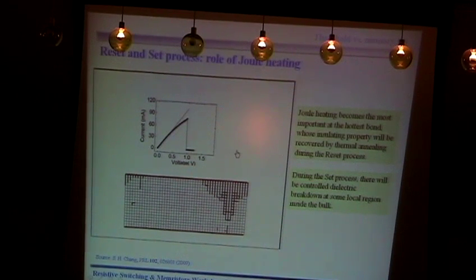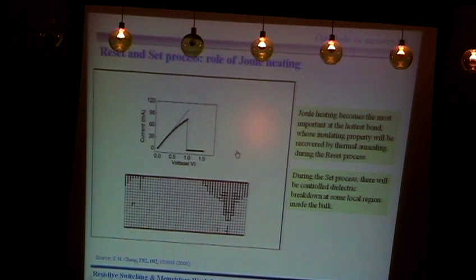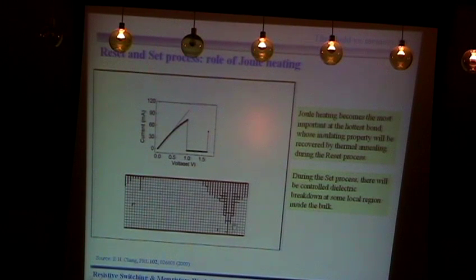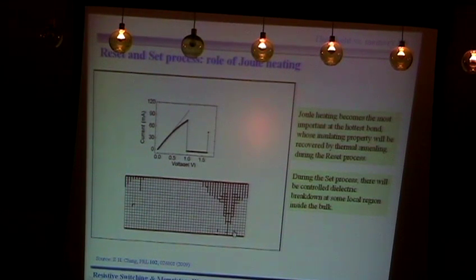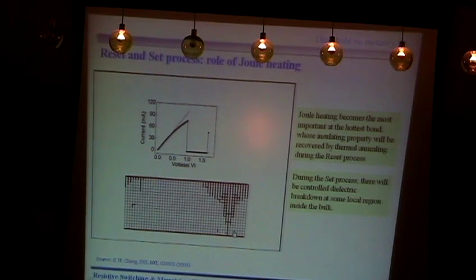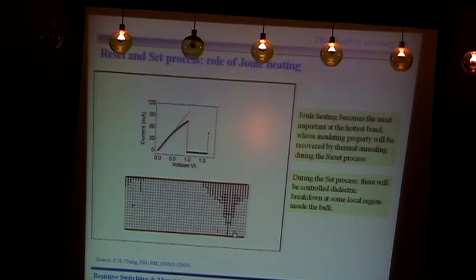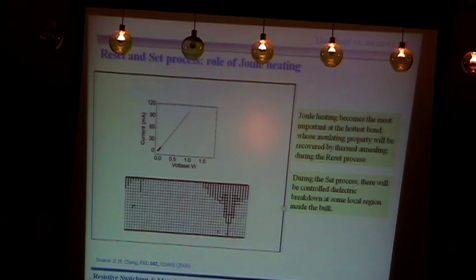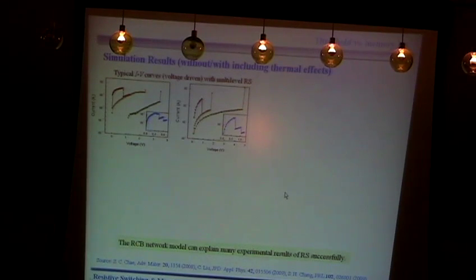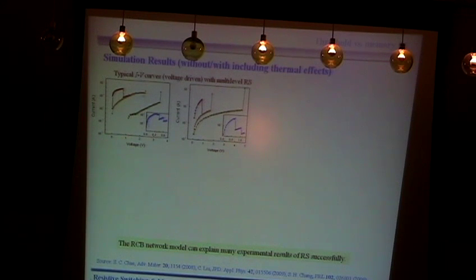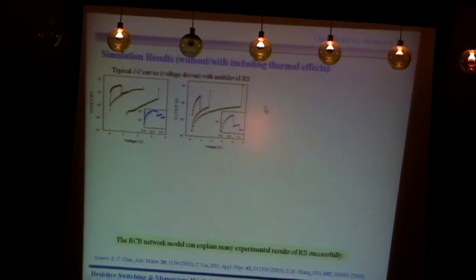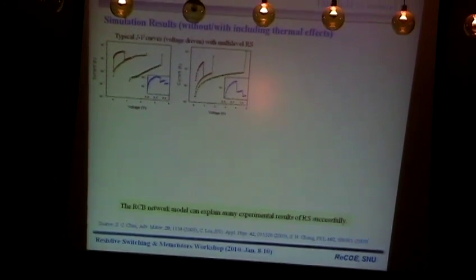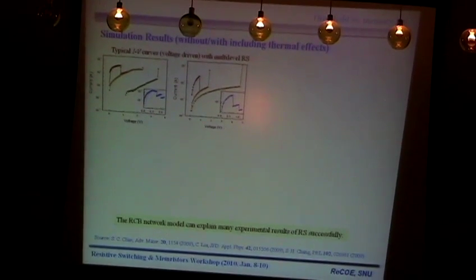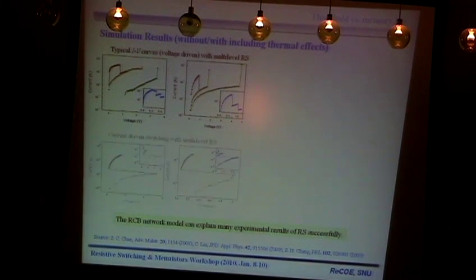Then if you keep increasing your voltage, this region will experience another breakdown, so it will recover. That one is the reset process, and the other one is the set process. With this simple model, we did a lot of simulations. First, I will show you some simulations done with and without the Joule heating. They actually give the same result, so I'll show those results first.